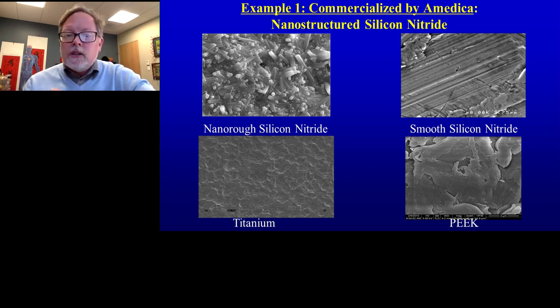So we followed our equation. Again, we plugged in what's the starting surface energy of this silicon nitride sample, what's the protein we want to absorb that can both increase bone growth and decrease bacteria growth. We calculated out the Z height, the X width, the Y length, and the nano rough silicon nitride, the image here in the upper left, is what we got. So this is the exact dimensions of nanoscale features that our equation told us we should create to reduce infection.